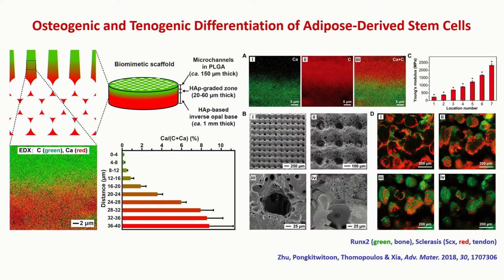And then we seed this scaffold with adipose-derived stem cells, and then we look at their differentiation. In this particular study, we look at two different types of markers. One is RUNX2, that's the indication of osteoblasts. And then we also look at scleraxis. This is a different type of marker. This is the marker for tendon. So this is just the 4 different regions along the cross-section. You can see when you move from the polymer side to the bone side, you are going to see a gradual increase in green intensity. That's osteoblast numbers. And this red one, you can see the opposite trend. So on the polymer side, you see more tendon cells, and on the bone side, you're going to see very few tendon cells.